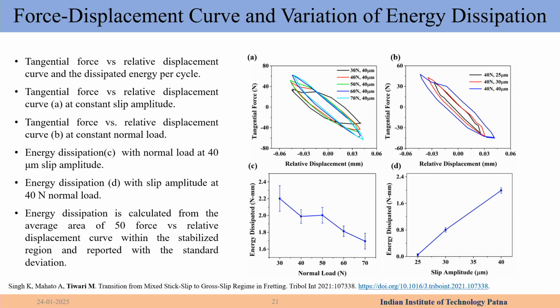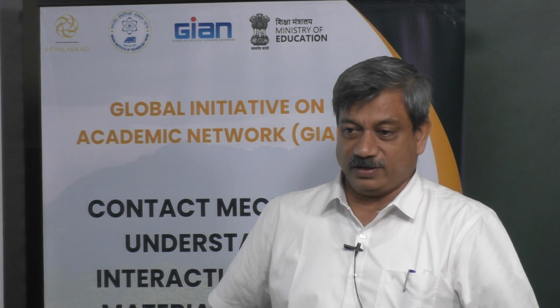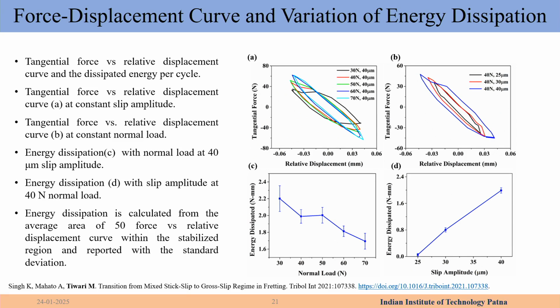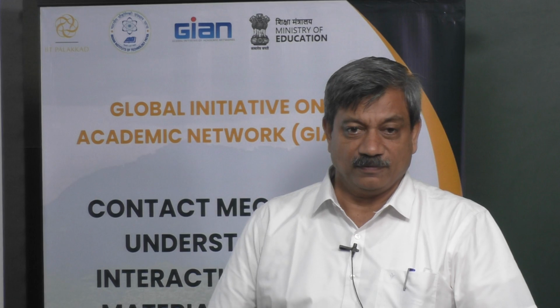Of course, there is more work which has been done on this. It's reported in the paper; this is a Tribology International paper. We've also found out the energy dissipated for sliding, tangential force versus relative displacement, for different conditions, where we change the load and keep the peak to peak displacement the same, and in the other case we keep the load the same and change the peak to peak displacement. You can see that the energy dissipated reduces with normal load. You increase normal load, the energy dissipated reduces. So if you are trying to find out the damping or something like that, this is a good indicator. And with slip amplitude, as it increases, energy increases; more heating is going to happen as the slip amplitude increases.